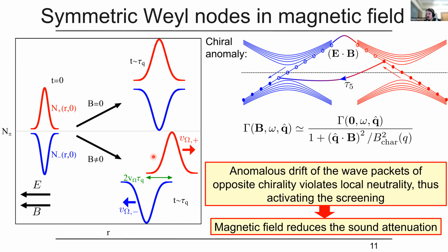It's actually an interesting question, what will happen in topological insulators. Naively, I would expect the effect to remain. But first of all, there is no chiral anomaly there, so what are we even talking about? But there might be some effect of another kind related to this. Just to clarify, for a two-dimensional Dirac spectrum, there is no chiral anomaly, so this effect will not appear at all. There might be some other effect, which I don't know.